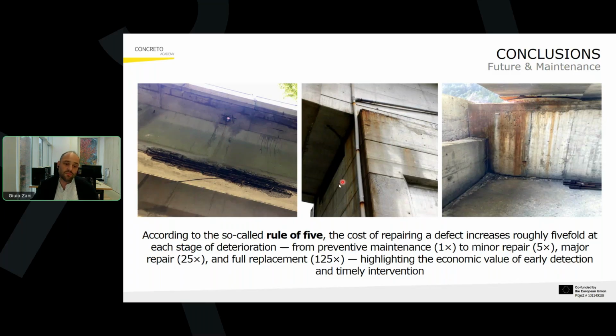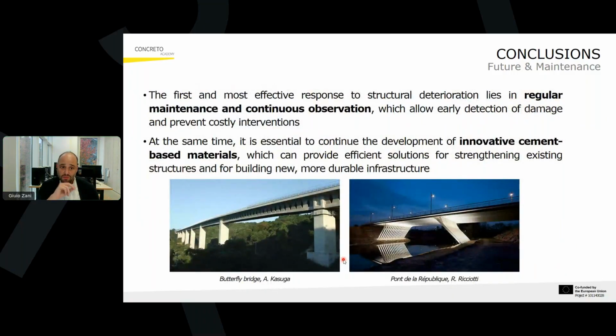And in doing this, it is important to always remember what we call the rule of 5. So if the cost of preventive maintenance is 1 and this is postponed, then you might have to introduce minor repair with a cost of about 5 times the original cost of preventive maintenance. If you avoid doing the minor repair, major repair might lead to a 25 times expense, and full replacement even to 125 times. Meaning that the growth of the economic burden of defects is exponential and not linear. So the first and most effective response to structural deterioration is regular maintenance and also continuous observation, which allow the detection of damage and prevent costly interventions over time.